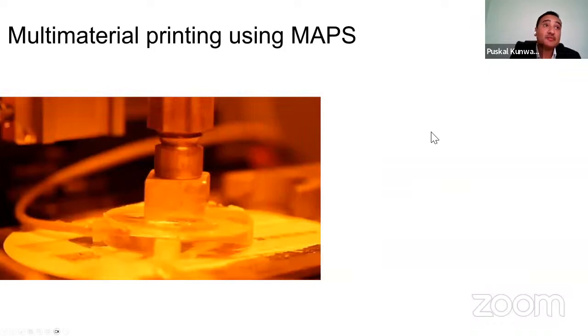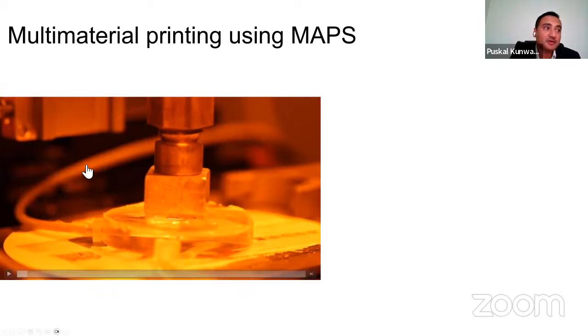Now we can do multi-material printing using MAPS. Just a little bit of background. There are two tubes, one tube for one material, and another tube right here for the second material. Once we flow a desired amount of resin that is printed, and almost all the resin is consumed, then we flow the other resin. So this helps us to print multi-material in the vertical direction without involving cleaning steps.